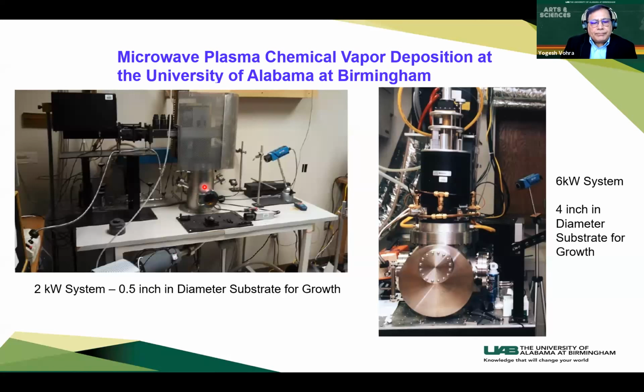We have a 2 kilowatt system, which is used mostly for homoepitaxial diamond growth. And we have a larger 6 kilowatt system, which is used for more polycrystalline growth of materials. The reason why we treat these two systems differently is that the system used for single crystal growth is ultra clean in terms of vacuum environment, because when you're talking about single crystal, you're talking about very pure materials.